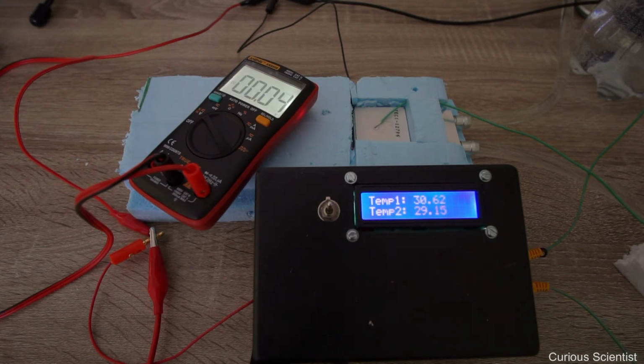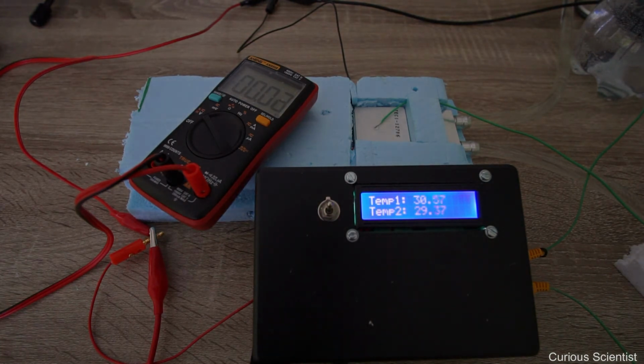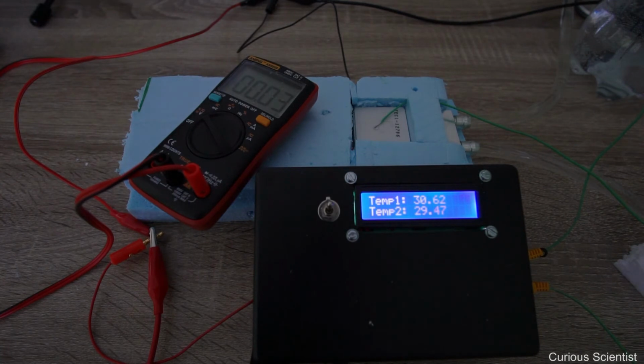And you can see from the speed of the heating that actually there is a huge heat flux between the two sides of the thermoelectric element. So it's very important to keep your hot side cool enough so you have the least possible heat leakage towards the cold side. So that's very important. And now you see that the temperatures are almost equivalent with each other. So there is like 1 degree Celsius difference, almost. So then we have like 20 millivolts.